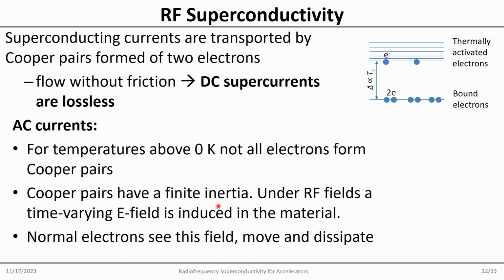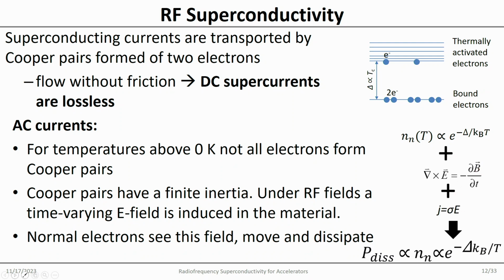Under a radio frequency field, they will induce an electric field in the material. Now if I have an electric field in the material, and I have normal conducting electrons there, these electrons will move under this radio frequency field, and they can scatter. They simply obey Ohm's law. So we have normal conducting electrons, following a Fermi distribution, with an induced electric field, Ohm's law, and this gives me my dissipation. My dissipation is proportional to the number of normal conducting electrons, which is proportional to this Fermi distribution. This is why under radio frequency fields we have intrinsic losses.